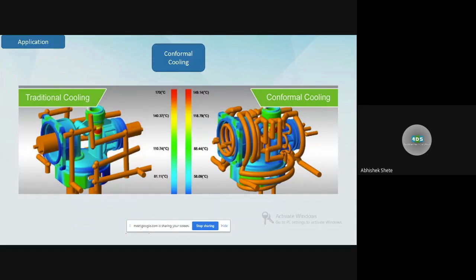But with traditionally manufactured molds, we can only have a cooling channel which is at 90 degrees like this. But if we can 3D print those molds, we can have the cooling channel along the profile of the mold. So what exactly is the advantage? It will immediately cool the part when we force a liquid material inside the mold. When we pass the coolant through the cooling channel, it can immediately cool that material. So your earlier 90 seconds of one cycle can come down to around 50 to 52 seconds.